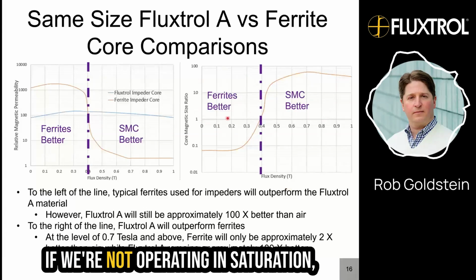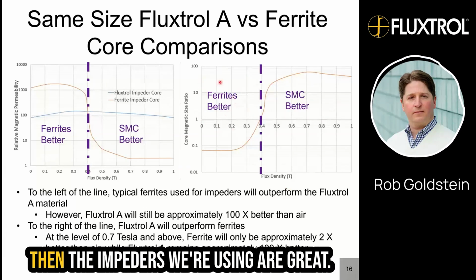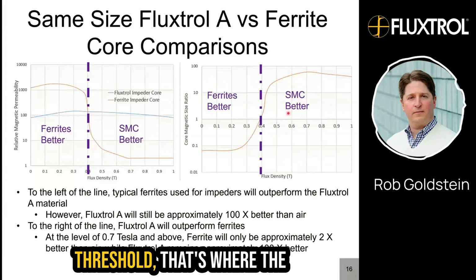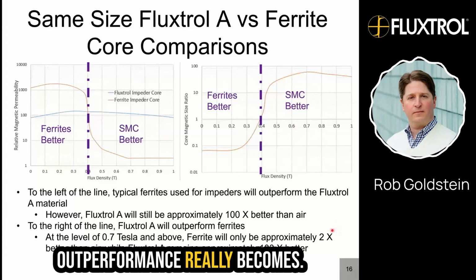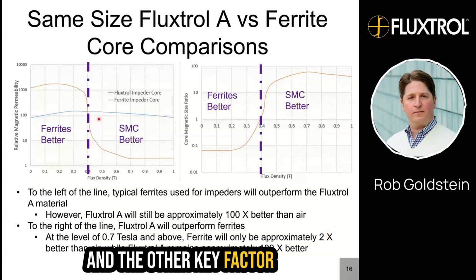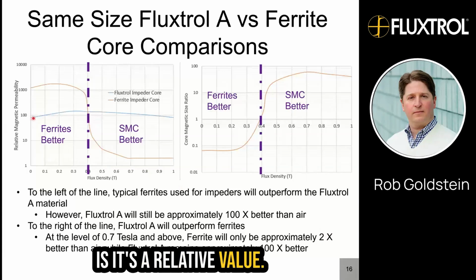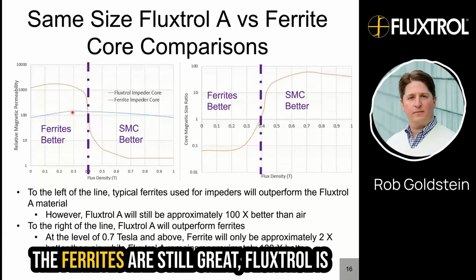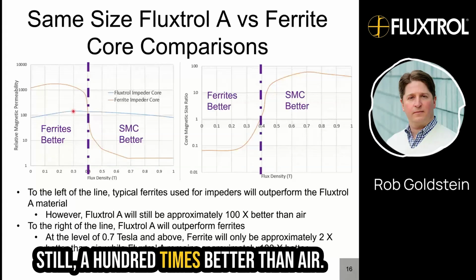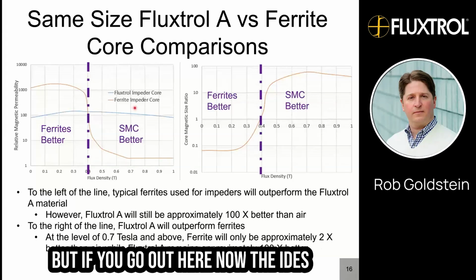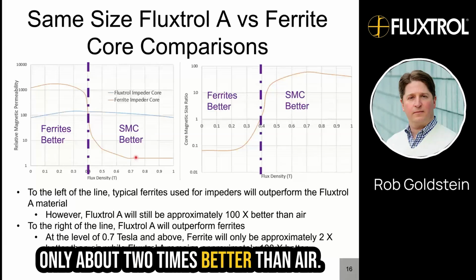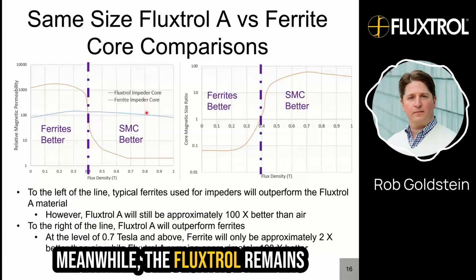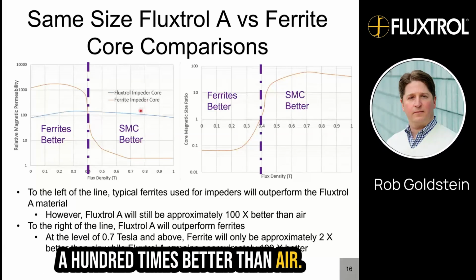If we're not operating in saturation, then the ferrite impeders we're using are great, but once we try to cross this threshold, that's where the outperformance really shows. The other key factor is that it's a relative value. Even if you look down here, where the ferrites are still great, Fluxtrol is still 100 times better than air. But if you go out here, the ferrite is only about 2 times better than air. Meanwhile, the Fluxtrol remains 100 times better than air.